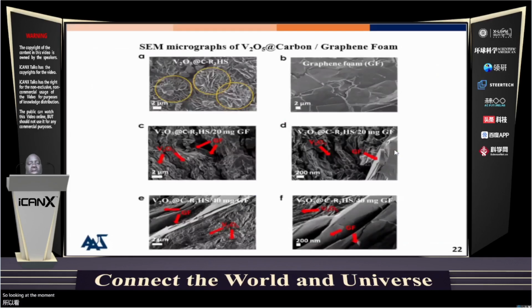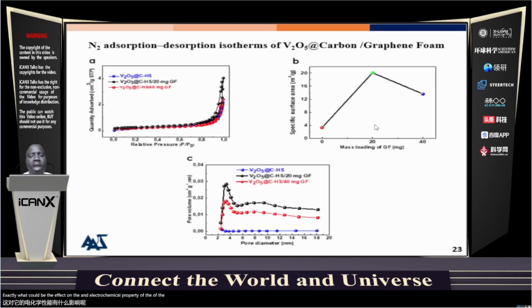Looking at the morphology with the SEM, we could see that it is completely different from the structure that we had previously before embedding the graphene into the composite. You could see that the morphology has completely changed, and it is more compact when we embed 40 milligram of graphene than 20 milligram of graphene. We will see what could be the effect on the electrochemical property of the material. We also look at the BET to see how the material is nanostructured, and we could see that the surface area of the material increases.